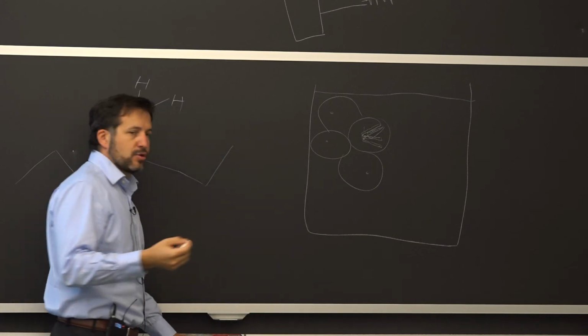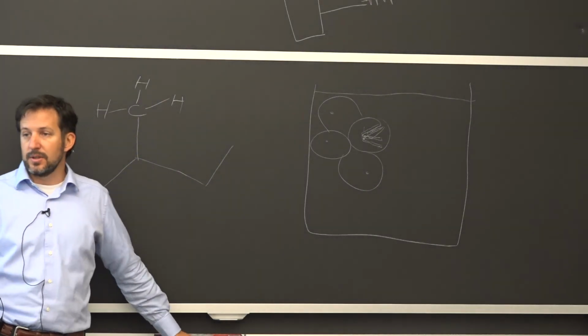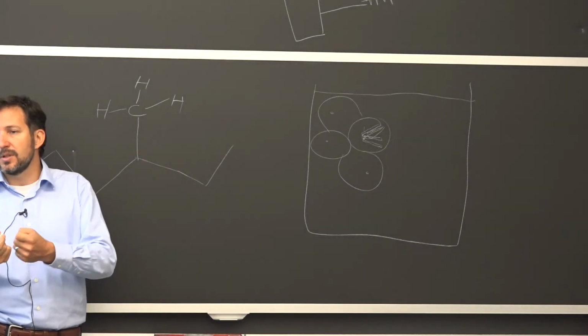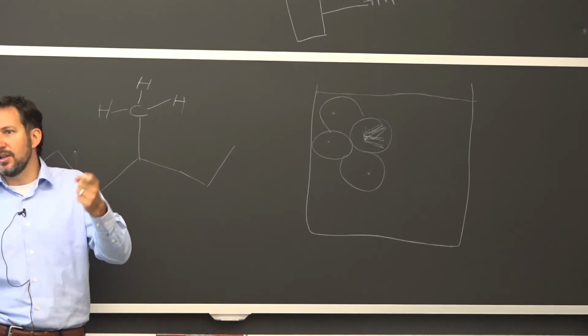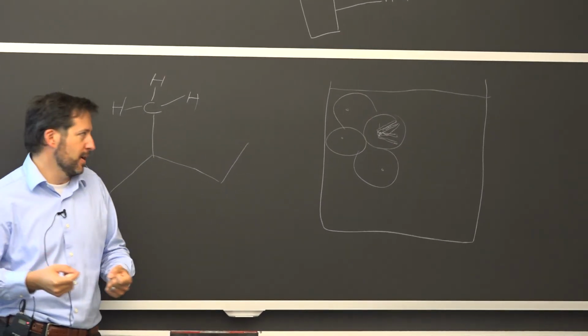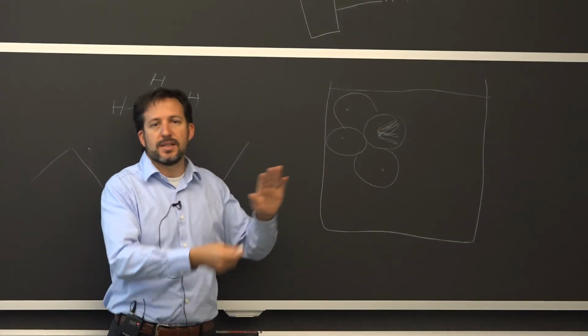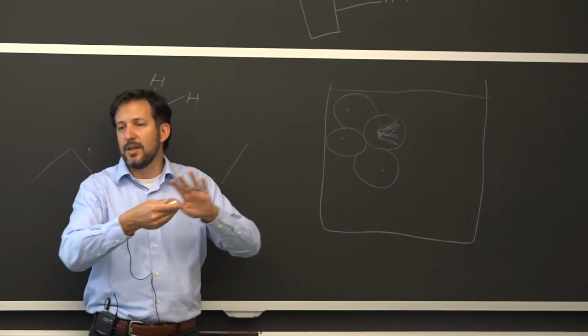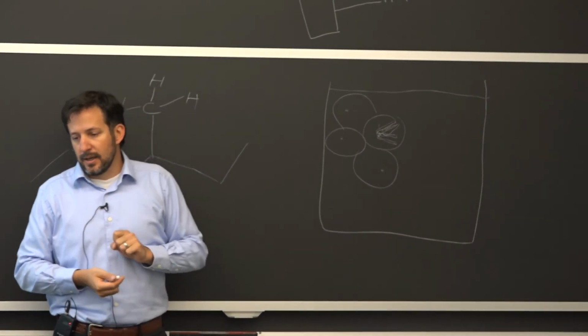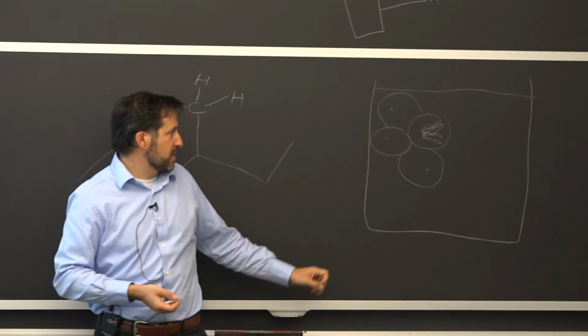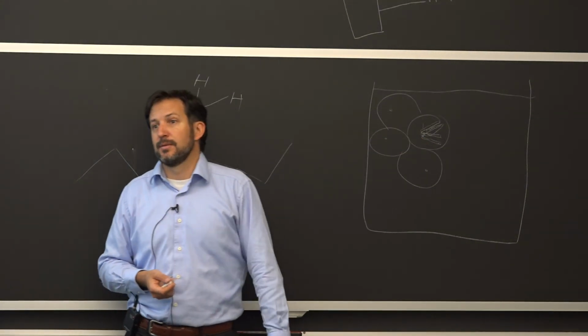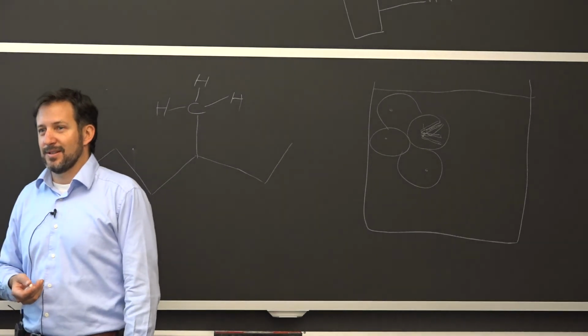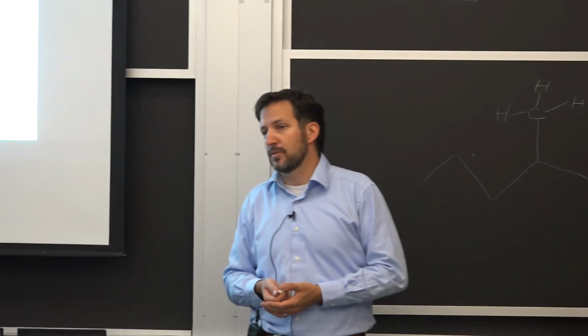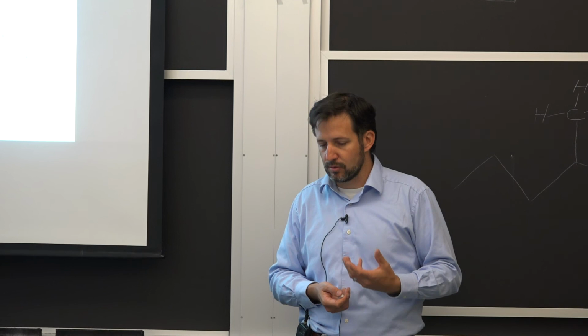The crystallite is very strong in terms of its yield strength. If you try to deform that crystal, it takes a lot of energy because the dislocation in there is very complex. What's easy to stretch is this amorphous zone between the crystallites. If it wasn't for having crystals in polyethylene, we couldn't use it, even for water bottles, because it's too soft as far as the amorphous portion of it is concerned. It's the crystallites that make it strong.